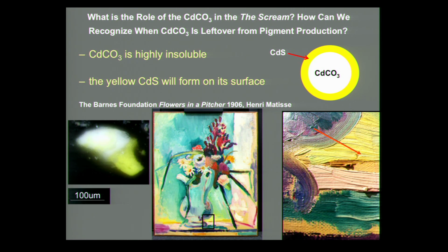So what about the role of cadmium carbonate in the Scream? How are we going to recognize when cadmium carbonate is actually present as leftover material from the production of the pigment? Well, it turns out that cadmium carbonate is a highly insoluble material, and so when it's used in order to make the yellow cadmium sulfide, the cadmium sulfide actually forms on the surface of the cadmium carbonate.